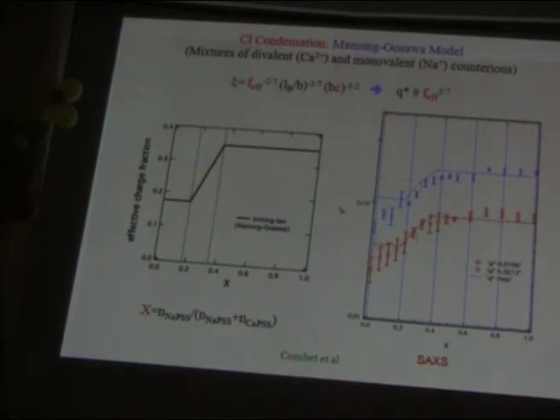Another point: you are able to measure the effective charge by the position of this electrostatic peak. That is demonstrated here. Here we have used mixtures of monovalent and divalent counterions. That is very simple. You mix two kinds of salt form of polystyrene sulfonate, and you obtain a change in the counterions. For this variable at 0 here, you have mainly the calcium counterions, and here you have mainly the sodium counterions. Of course, the condensation is not the same, so the effective charge is not the same for monovalent and divalent counterions. I won't go into the details, but you expect some figure like that from the Manning-Oosawa model, because when you mix divalent and monovalent counterions, first you condense the divalent.